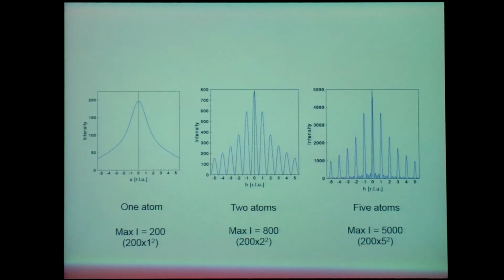Now this is also why we want a crystal, because we would get diffraction from a single molecule, but it would be a very boring diffraction picture that would look like a diffuse kind of pattern. As soon as we start building up the number of molecules, we amplify that. We not only get constructive interference because we've now got a crystal, but we amplify the signal that we get out. So this is also why single molecule imaging is very difficult, because the signal that you get is very small compared to a crystal. You need a high intensity beam and very, very low noise.